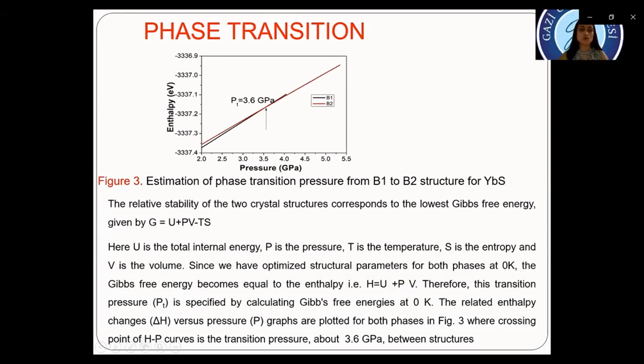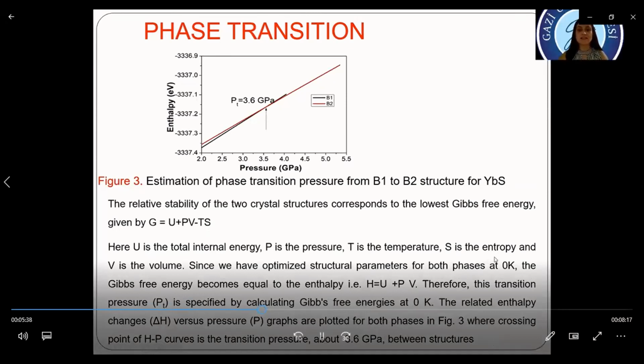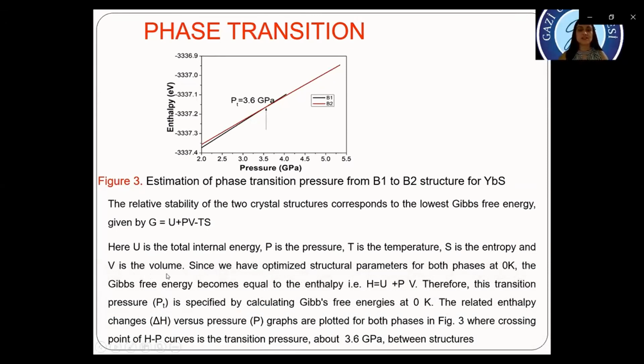The relative stability of the two crystal structures corresponds to the lowest Gibbs free energy, given by this equation. Here, U is the total internal energy, P is the pressure, T is the temperature, S is the entropy, and V is the volume. Since we have optimized structural parameters for both phases at 0 Kelvin, the Gibbs free energy becomes equal to the enthalpy. Therefore, the transition pressure is specified by calculating the Gibbs free energy at 0 Kelvin.